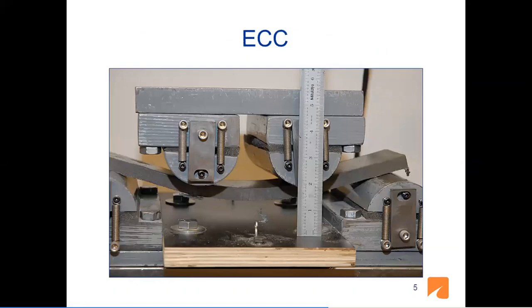Here is a good example of ECC, a small ECC beam. If you look on the web, you will find that ECC is also called bendable concrete. As you see here, and this is from our lab, this beam is very flexible and has undergone so much deflection, and you have very small, multiple cracks, but no large crack. So this is a bendable concrete, and we like to use it so that we can keep the cracks very tight, less than 0.1 millimeters, and chloride solutions cannot penetrate through those very tight cracks in our structures.